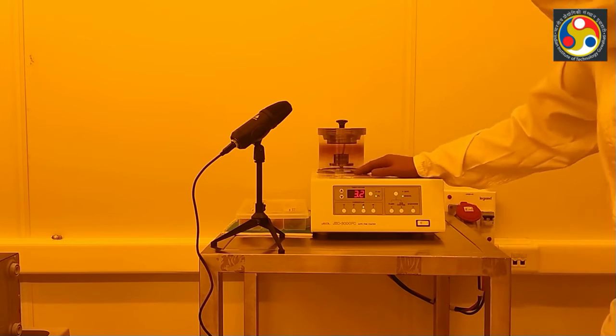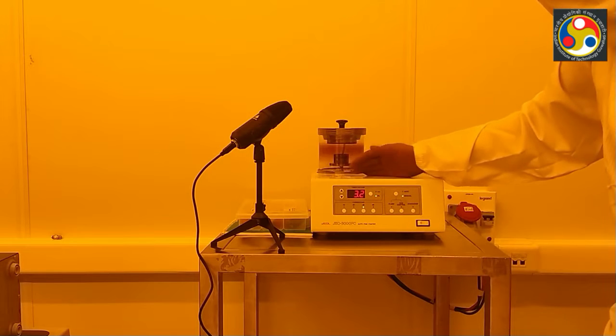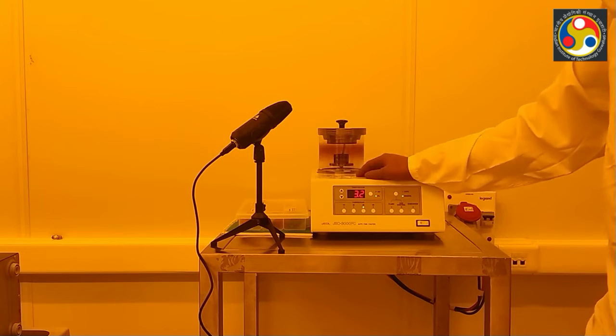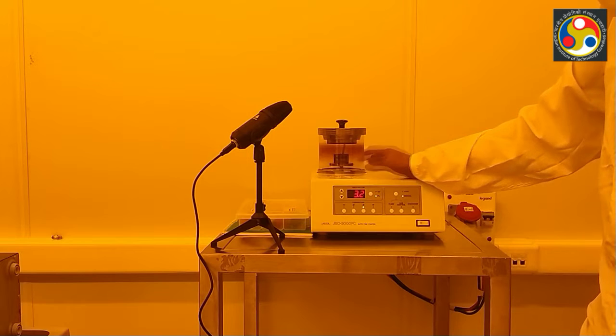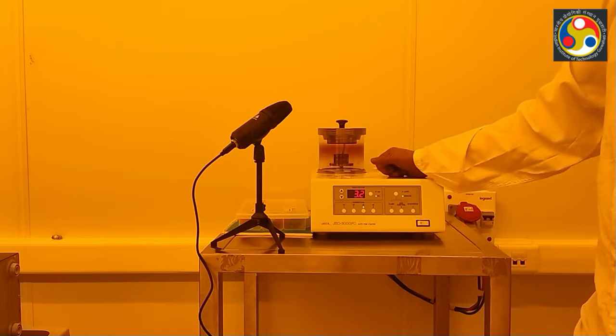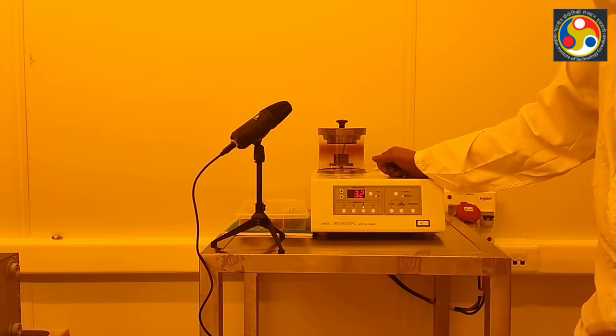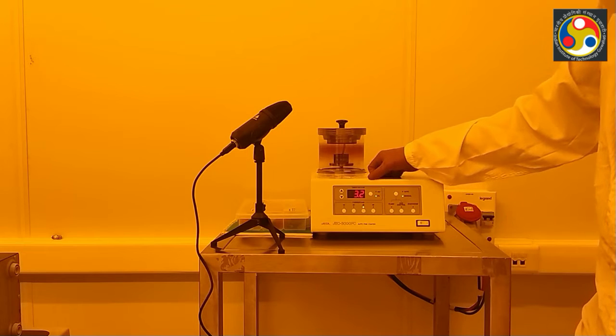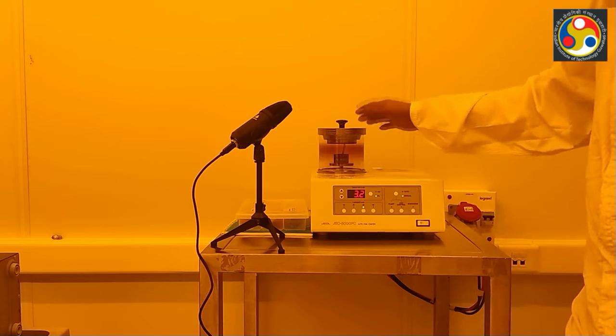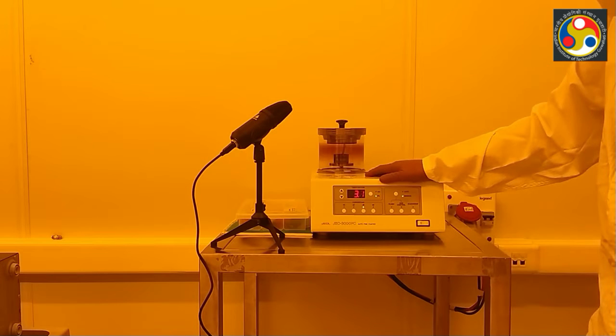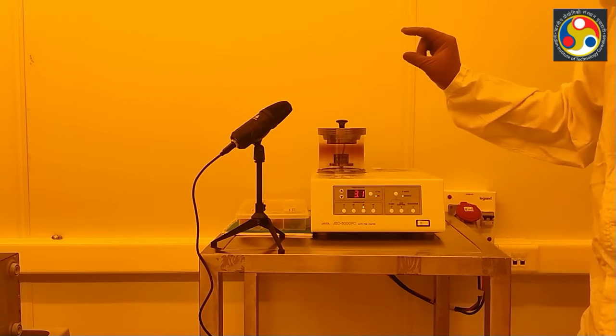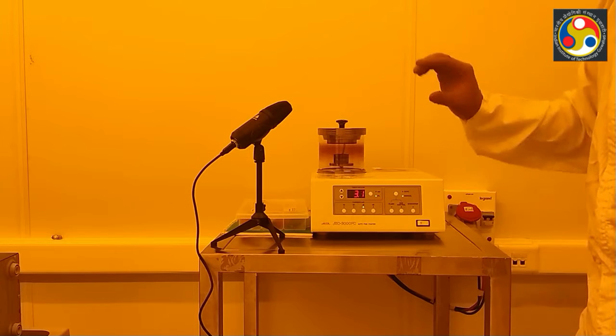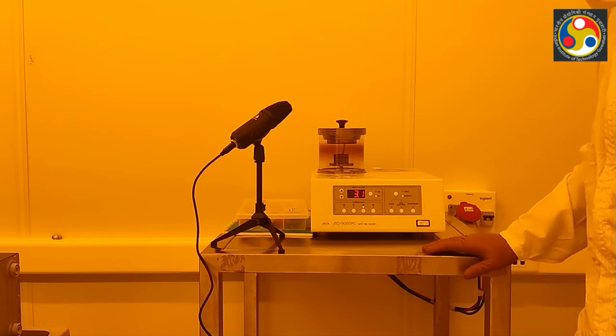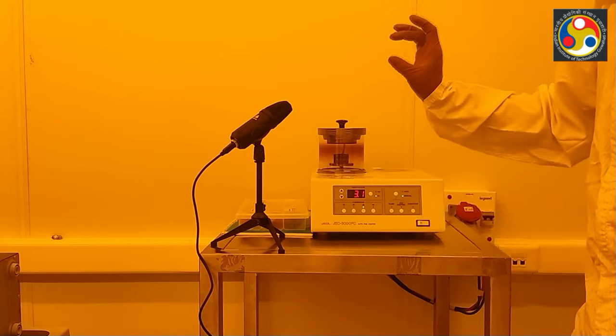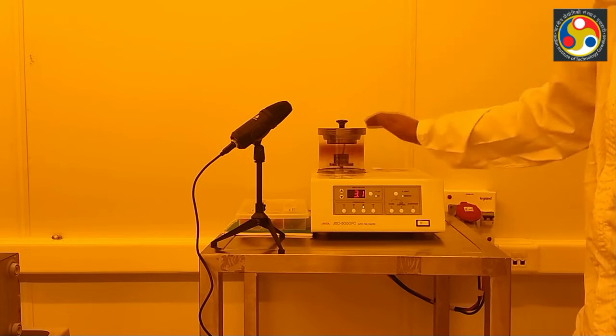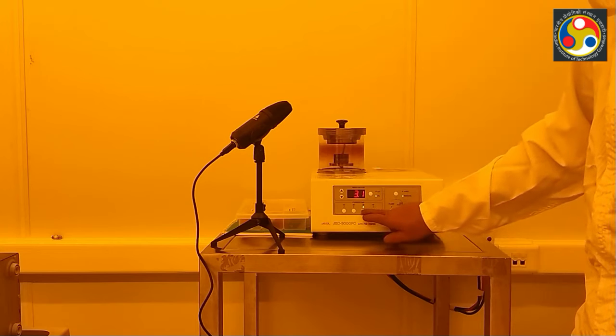Now the pressure inside this vacuum chamber is 3.2 Pascal. I can start the system when it is 3 Pascal, which is the recommended pressure for this. My sample is not highly semiconducting. It has a band gap of around 2.5 electron volt, so it is a moderately semiconducting material. So I need the platinum thickness to be moderate, not too much and not too small. In this system I can make a moderately thick platinum layer on top of my sample by using a current and a time.